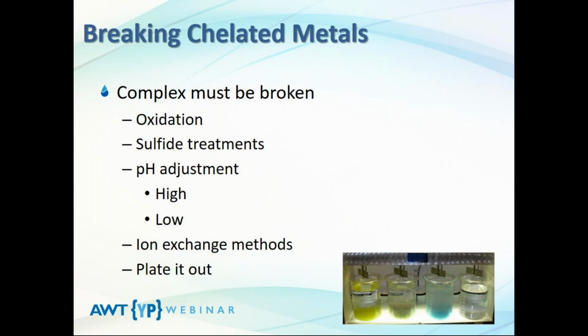Now, when I talk about plate out, I like hydrometallurgy. That's what I mean by here. When I've got chelated copper, you know what I do? I will go and I will get steel wool or powdered steel, and I will put it over in a tank, in a vessel, and I will introduce 1 amp of current to that bath. And even though the copper solution is not good enough for the plating bath, it's still going to be very high in concentration for waste treatment.